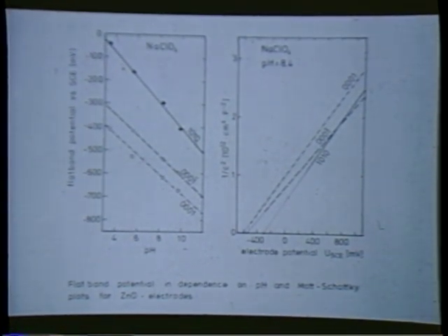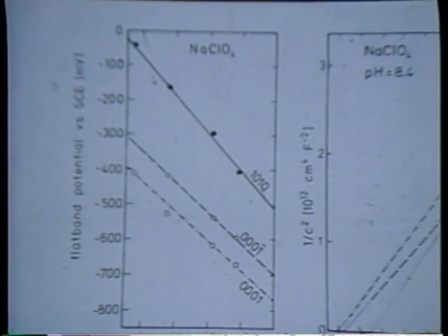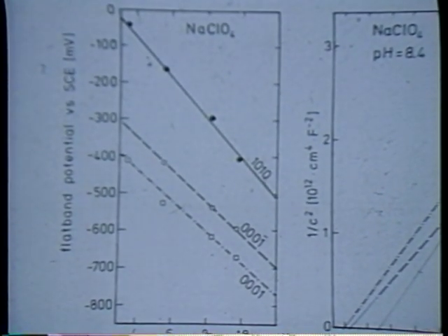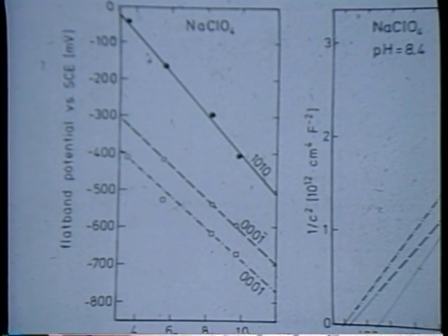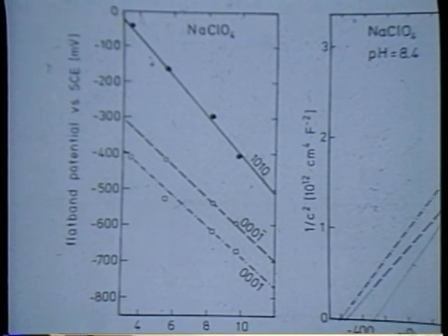a very common feature for oxides, where protons or hydroxide ions interact with the surface of the oxide, which is maybe to some extent hydrolyzed to the hydroxide. And here are the causes of flat band potentials. It depends on pH, and we see also another effect. The flat band potential depends, obviously, on the orientation of the crystal surface. Again, that is obvious because the flat band potential is related to the work function of materials. The work function depends on the crystal orientation.